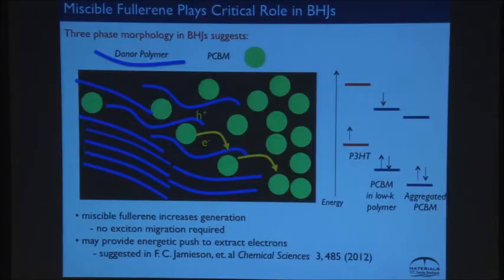And what you see is that the ones that are more miscible have this rather steep dependence of mu tau on light intensity. So this is kind of a surrogate for charge concentration. And the one that performed a little bit better, that was a little less miscible, actually was a little more flat. You'd expect if it were just trap dominated, it would be completely flat. But you never quite get there in a lot of these cells. So we see a steep change in the recombination mechanism between the two.